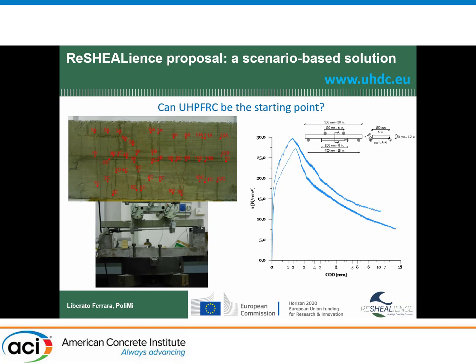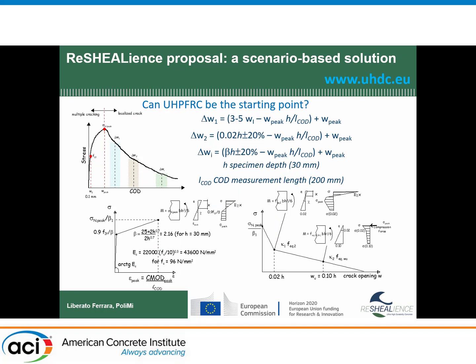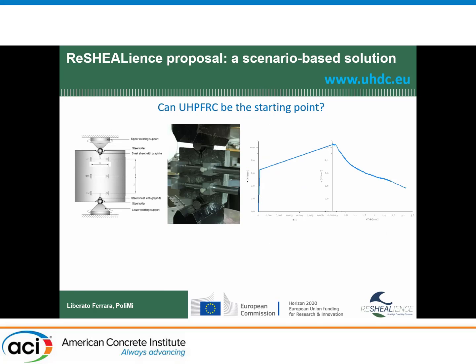As a matter of fact, we were speaking about multiple cracking. You can see this is about 200 millimeter spacing on our specimen. We got a lot of cracks, and we got about 30 MPa flexural strength. And obviously, we wanted to use it in design, so we employed a very simple true equilibrium equation procedure to back calculate the tensile stress-strain law before the localized cracking. And then obviously we have a softening law. And these are the results.